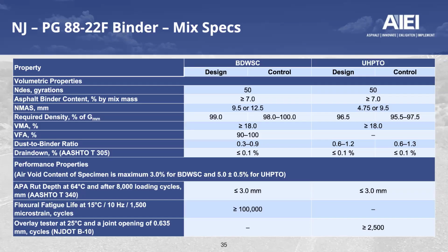They do have very high density requirements for both technologies, although the requirement on the bridge deck is even higher, with a range of 98 to 100%. So very close to zero air voids at the upper end, if they're hitting that sort of level. And with the thin overlays, they're targeting plus or minus a half percent, 95.5 to 97.5%.